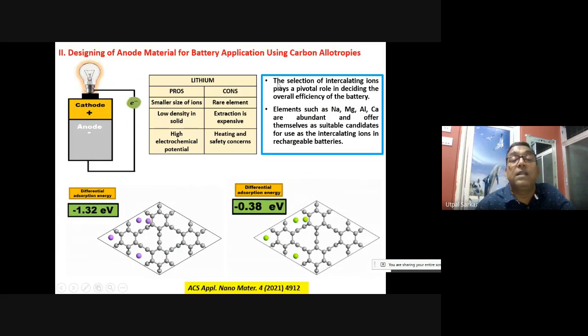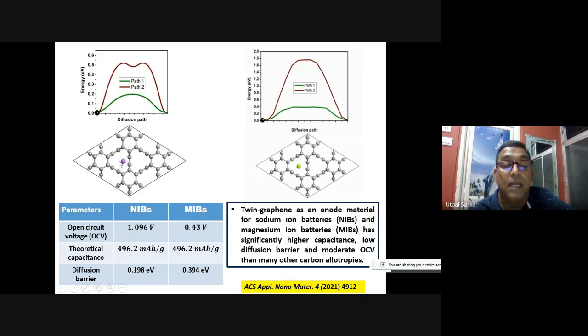Another work is on the same material as an electrode material. Here we have checked whether this particular carbon electrode can be used as an anode material or not. So here we have considered differential adsorption energy by putting one after another the sodium, magnesium, aluminum, and calcium ions, and checked how much it can adsorb. And what is the reaction energy needed to cause one to migrate over the surface?